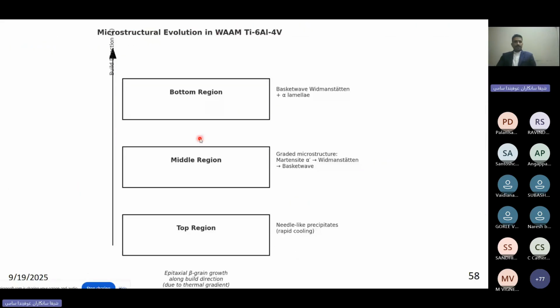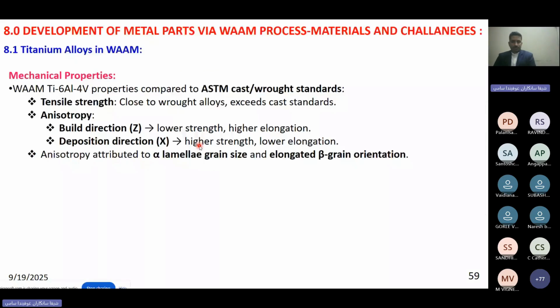This already explained you. Next, of course, mechanical properties. So people, I will show you some tables also. As I told you initially, the build direction has low strength, high elongations, whereas the strength along the transverse direction, they got very high value. Deposit direction, they got high strength, lower elongations. So this alloy also exhibited anisotropic properties because of the presence of different microstructure in the samples.